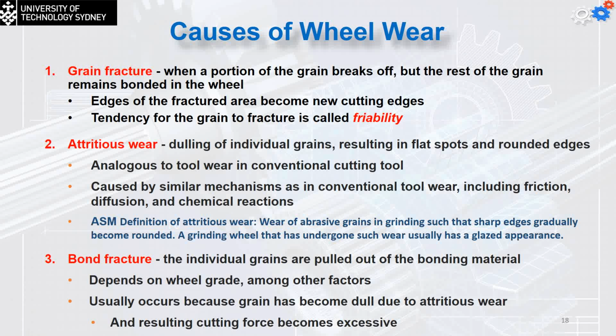It's analogous to tool wear in the conventional cutting tool, caused by similar mechanisms as conventional tool wear, including friction, diffusion, and chemical reactions. One of the other causes is the bond fracture itself. The bond holding the particles starts to fracture, due mainly to the high temperature. Depending on the wheel grade, among other factors, it usually occurs because the grains become dull due to attrition of the wheel, and the resulting cutting forces become excessive, so the wheel will simply shatter because of this fracture.